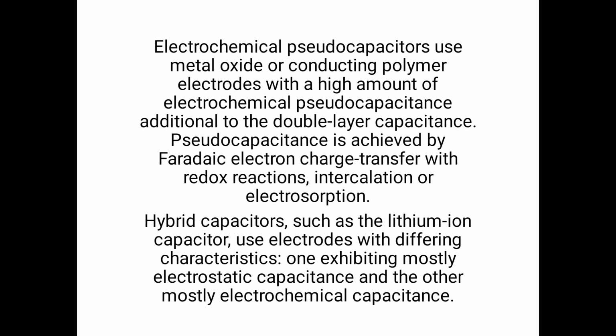Electrochemical pseudocapacitors use metal oxide or conducting polymer electrodes with a high amount of electrochemical pseudocapacitance additional to the double layer capacitance. Pseudocapacitance is achieved by Faradaic electron charge transfer with redox reactions, intercalation or electrosorption. Hybrid capacitors such as the lithium ion capacitors use electrodes with differing characteristics, one exhibiting mostly electrostatic capacitance and the other mostly electrochemical capacitance. Thank you.